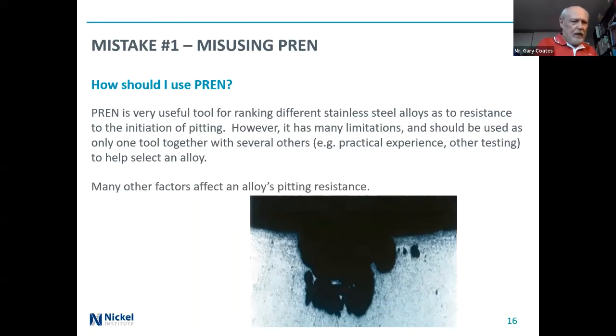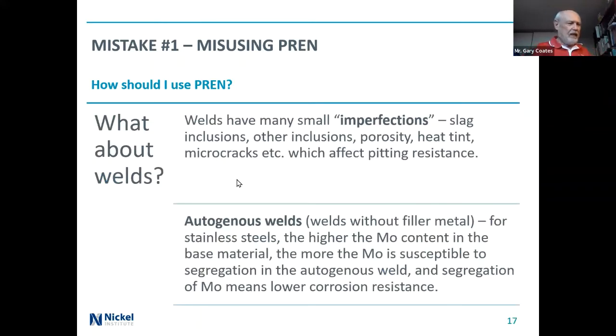As we said, there are many other factors that affect an alloy's pitting resistance. So what about welds? This is a welding group, and we have to remember that welds have many small imperfections. Slag inclusions, even if they're not large, if you look under a microscope at say 50 power, you will see that there are tiny little slag particles that might be in the surface. There are other inclusions, porosity can exist, and again, it may only be seen if you look at a high enough power. Heat tint, micro cracks, they all affect pitting resistance.